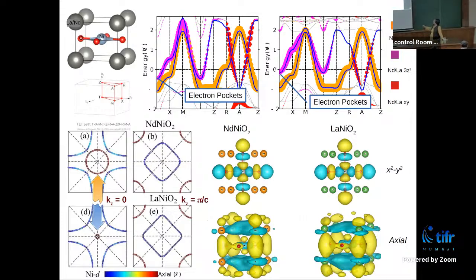If you see the Fermi surface of this compound, one shown for neodymium nickelate, another for lanthanum nickelate, you have this whole large pocket exactly like the cuprate, which is shown in red. And in blue are these electron pockets, which are created by this band, a hybrid between your rare earth or lanthanum 5d states, which are generally empty, as well as a mixture with the nickel s. Again, the s is a very important object. First of all, it's empty and it's spherical, so it can do a lot of things by coupling with others.